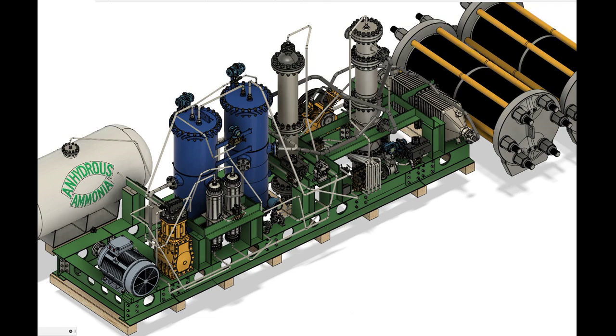For illustrative purposes, we calculated the mass and volume of a typical large-scale ammonia converter using a patent drawing, which was used to surmise wall thickness. The weight versus catalyst volume of benchmark ammonia converters is estimated using three-dimensional CAD modeling of a 2D image. To confirm the veracity of the inferred 3D estimation, we compare to an ATB Riva Calzoni reactor, whose dimensions and weight were published. For the inferred 3D reactor, the catalyst volume is 30 cubic meters, and the dead weight of the reactor is 252,000 kilograms.